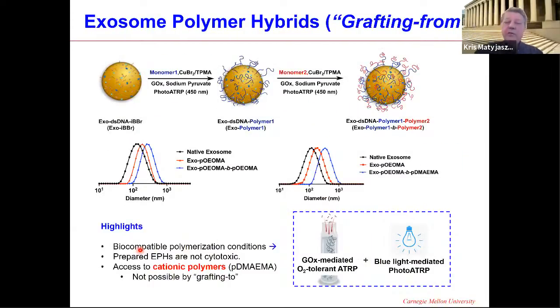Now, if you go to a grafting from process, it's very interesting because you can make a block of polymers, you can make chain extension. This is done under very mild conditions, with glucose oxidase and a blue light process. It can be done either way. And you can make blocks of polymers, in fact, with a cationic process. You cannot do this cationic process by grafting onto because it would interfere with the membrane and with the DNA as such. So this is access to cationic polymers this way.